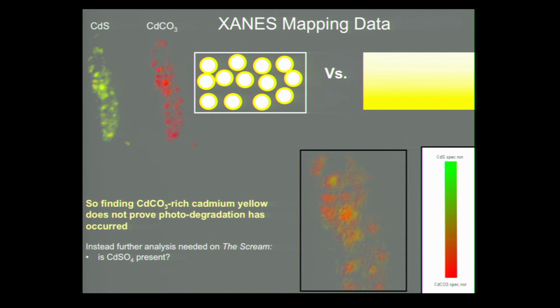And so really what we're looking for in terms of trying to identify if cadmium carbonate is a leftover starting material or if it's a photodegradation product is this type of microstructure in the paint versus this type of microstructure in the paint. And so finding cadmium carbonate in the Scream is not enough to tell us what the mechanism of degradation is that is happening in the Scream. We really need to go on and do further analysis, for example, definitively finding out whether cadmium sulfide is present, and also finding out if any cadmium carbonate is collecting up at the surface of the paint layer.